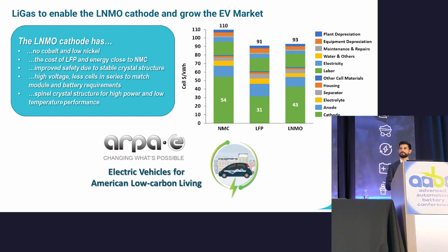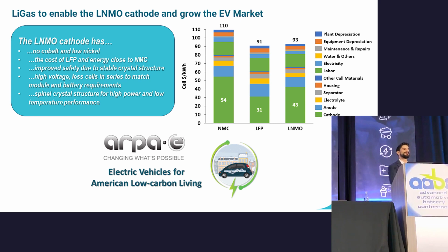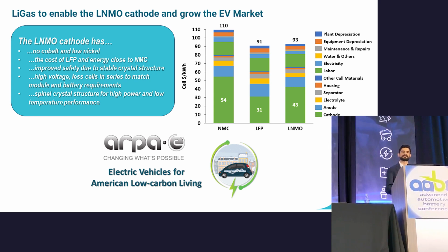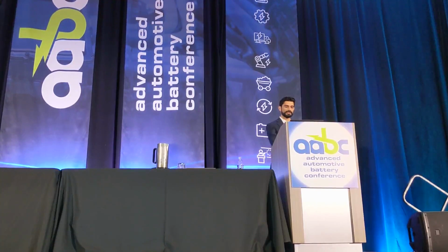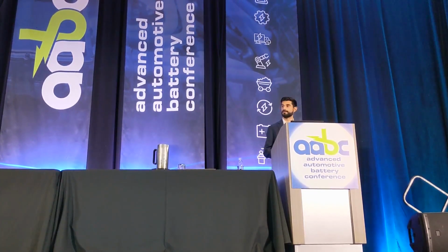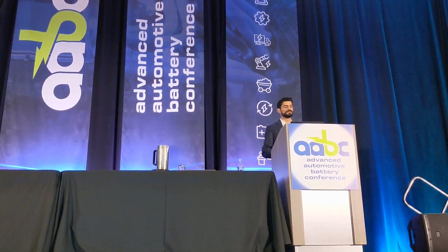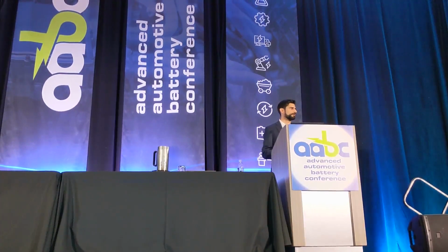But the problem with this cathode all along has been the high voltage stability of electrolytes. Because it's operating at such a high voltage, these electrolytes tend to break down, and you get very little cycle life out of very little performance. So we believe our LiGas chemistry is actually an enabler for this high voltage cathode. And so we actually have won an award from ARPA-E to explore this cathode specifically, and we are working with project partners to that end.